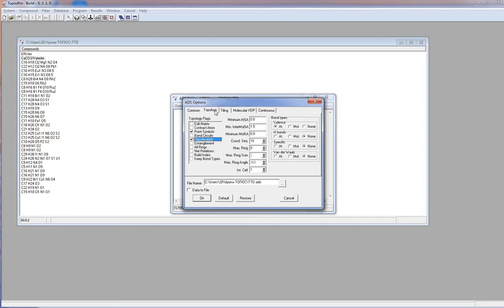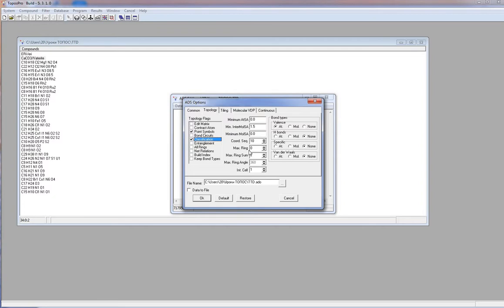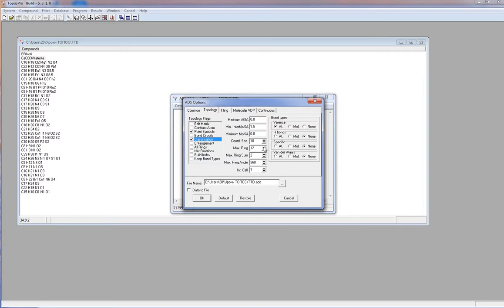Max-ring parameter calculates vertex symbols. Vertex symbol gives similar information as extended point symbol, but only for rings. It should be noted that in most cases coordination sequence and extended point symbol set is sufficient to classify net. And calculation of these parameters is rather fast. When you set max ring size, you should specify the biggest ring in the structure. Of course, you don't know exactly the size of the rings, so better set max ring equals to 10 or 12, because it is enough for most structures. You should remember, the larger the maximum ring size value is, the slower calculation will be.